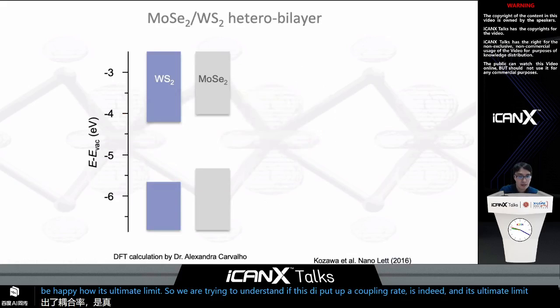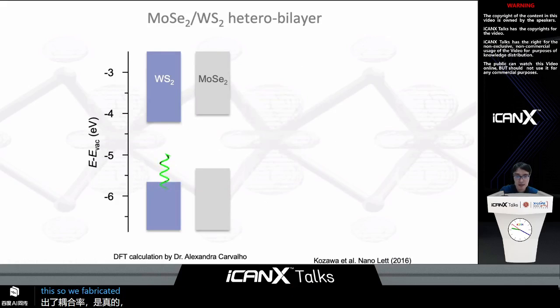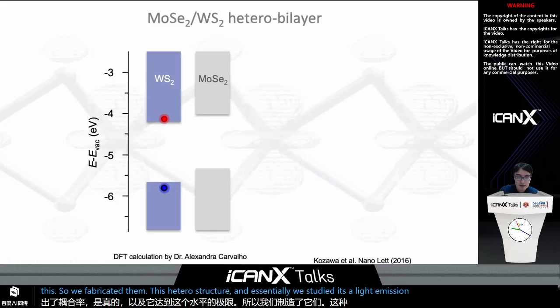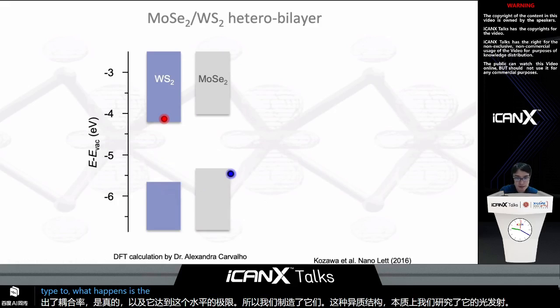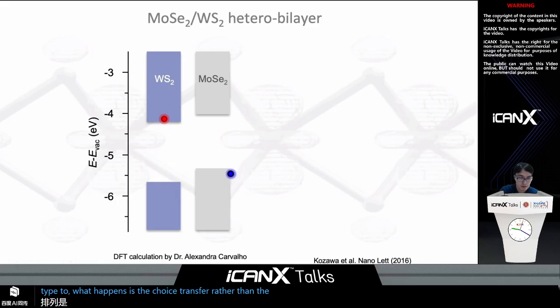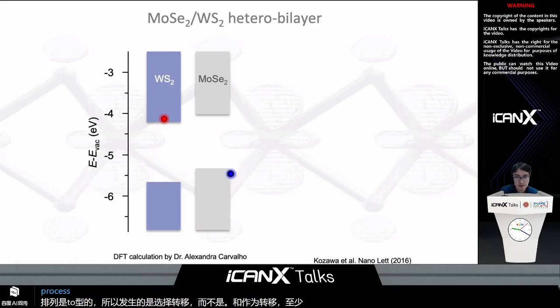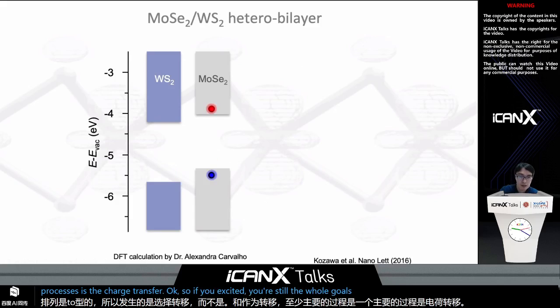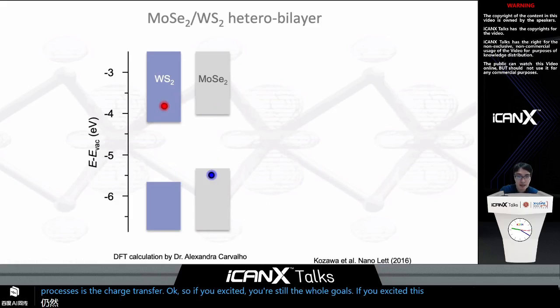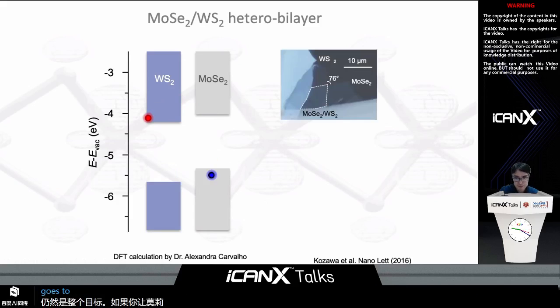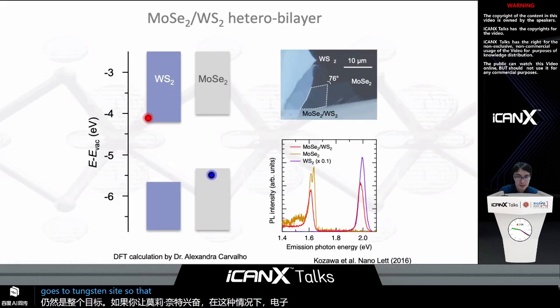To measure this, we fabricated this heterostructure, and essentially we studied its light emission. But because the band alignment is type 2, what happens is charge transfer rather than energy transfer. At least the dominant process, one of the dominant processes, is charge transfer. So if you excite WS2, the hole goes; if you excite molybdenum selenide, in this case, the electron goes to the tungsten side. That results in the quenching of the emission in both layers, which doesn't give us too much information.